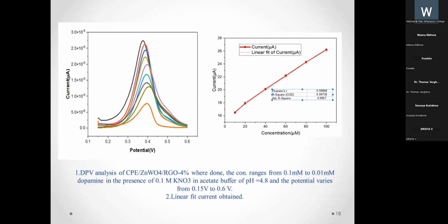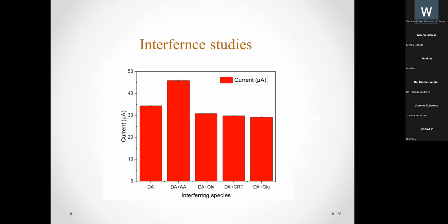And here the DPV represents a concentration ranging from 0.1 millimolar to 0.01 millimolar dopamine in the presence of 0.1 molar KNO3 as the supporting electrolyte in an acetate buffer of pH 4.8, and the potential varies from 0.15 volt to 0.6 volt. The corresponding linear fit graph was also obtained, and Pearson's R value was obtained about 0.9967.